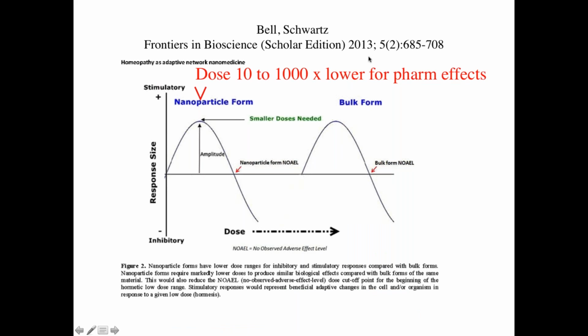This is another publication, from 2013. So basically what happens when you're using nanoparticles, compared with the bulk form, is a hormetic curve, where high doses cause inhibition, and lower doses down to the no observed effect level, the no observed adverse effect level. Toxicologists generally only look to here, but if you keep going down, you find there's a stimulatory effect. In the bulk form, that curve is shifted this way. For nanoparticles, it's 10 to 1,000 times lower for similar effects. Smaller doses are needed for a similar amplitude effect.